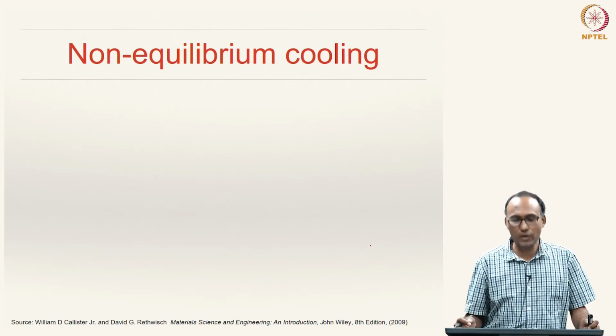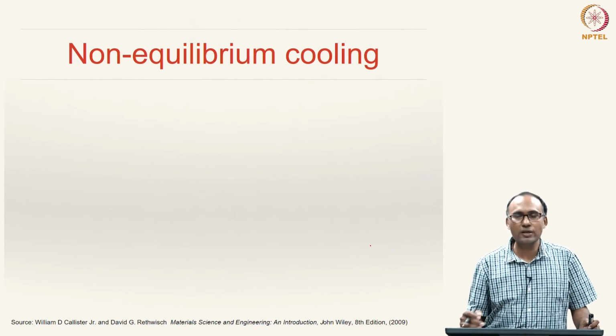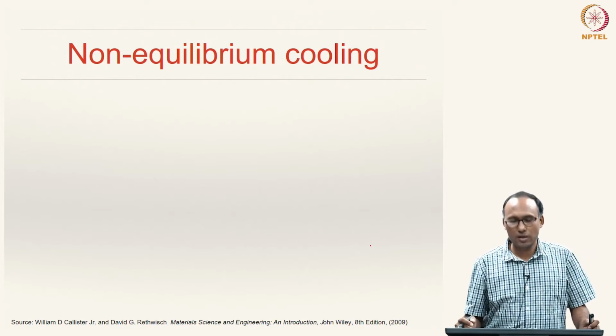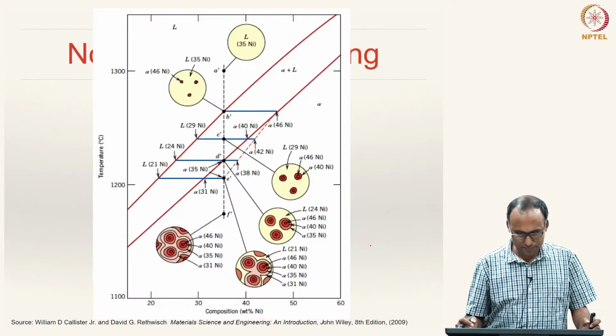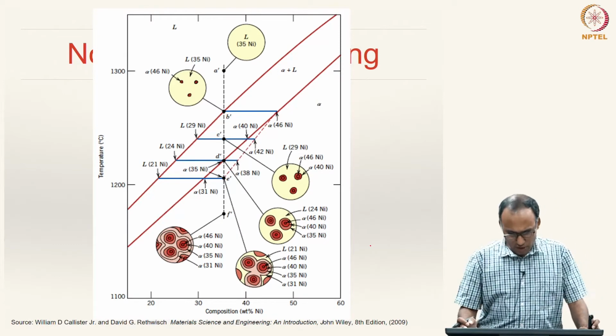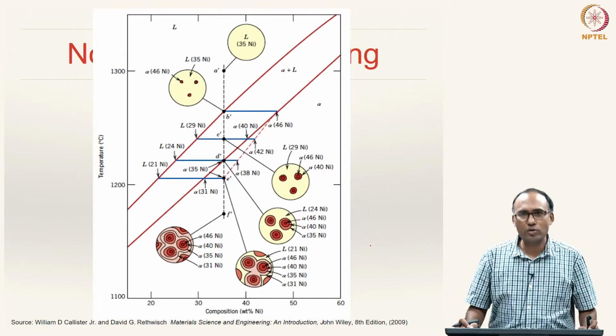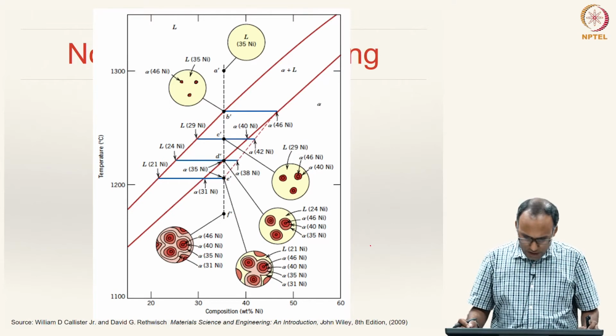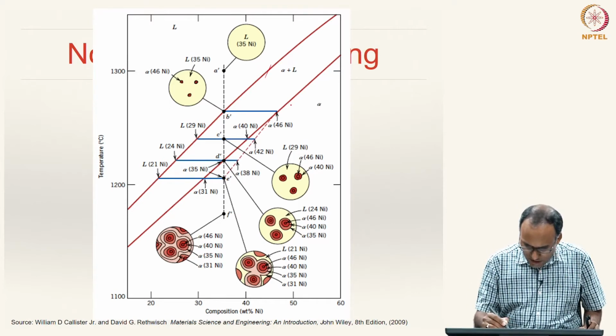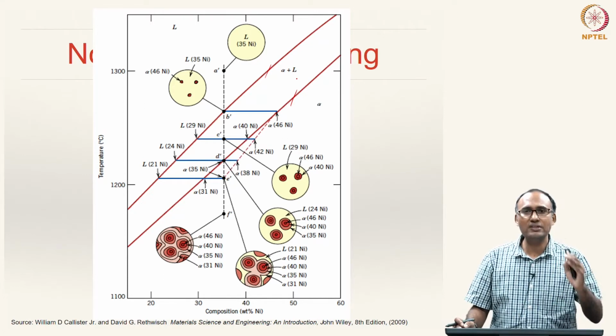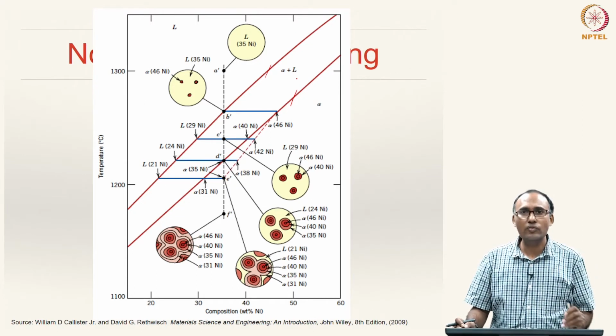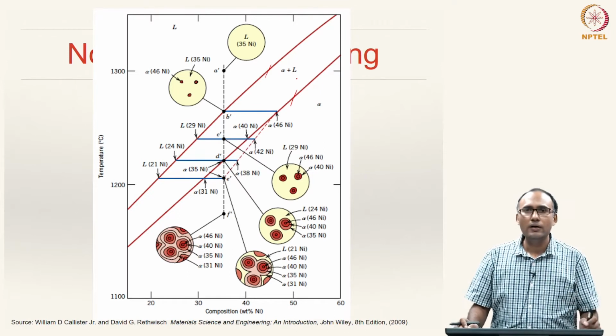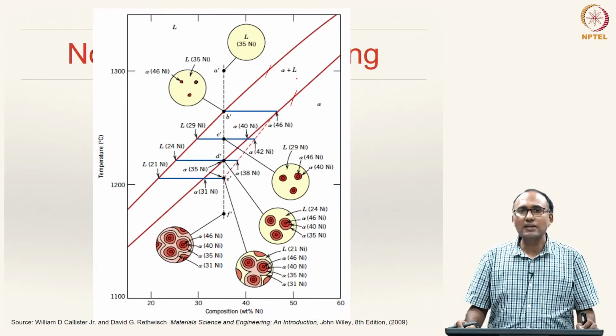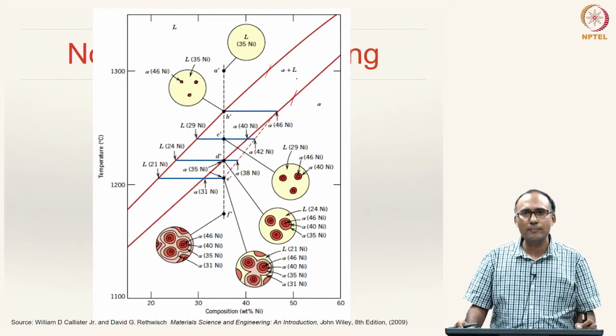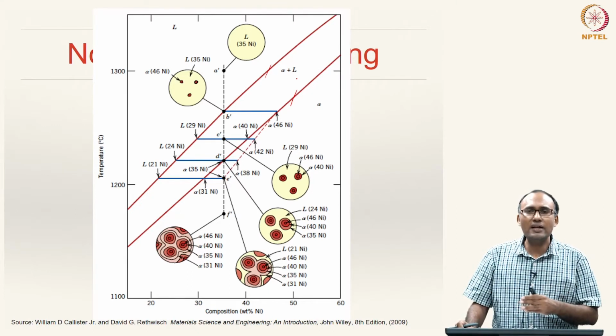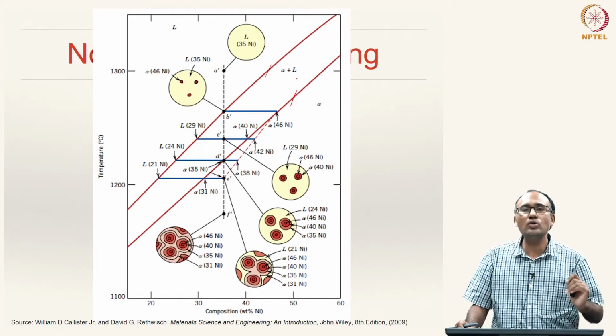And what happens if you have such a cooling rate, and what will that lead to in the changes in microstructure? Okay. So, this picture represents the evolution of microstructure for non-equilibrium cooling. Here the two red solid lines represent the solidus and liquidus lines for equilibrium cooling, and here what we are assuming is that in the liquid state the equilibrium exists, and only in the solid state there is no equilibrium.